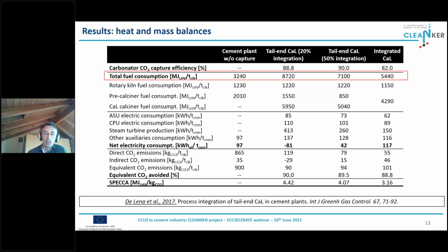Okay, in this table, we have the main results of the configurations that we envisaged. First of all, we can see that the two tail end configurations feature a steep increase in the fuel consumption compared to the first column, which is related to the cement plant without capture. And this is mainly related to the low thermal integration with the host cement plant, and also to the effect of the double calcination. Indeed, each CO2 molecule which is captured by the tail end system experiences a first calcination in the cement plant calciner and a second calcination in the downstream calciner of the calcium looping facility. And this is a penalty for the system.